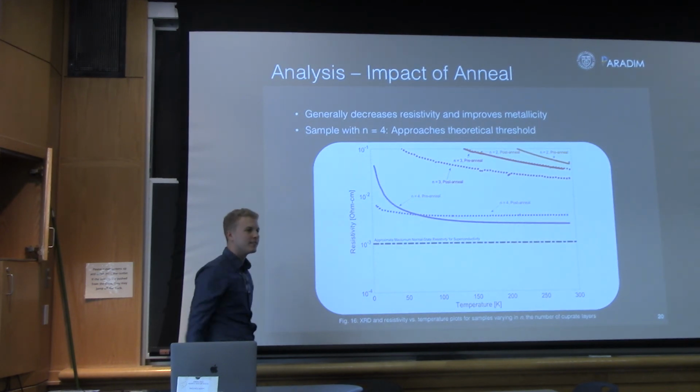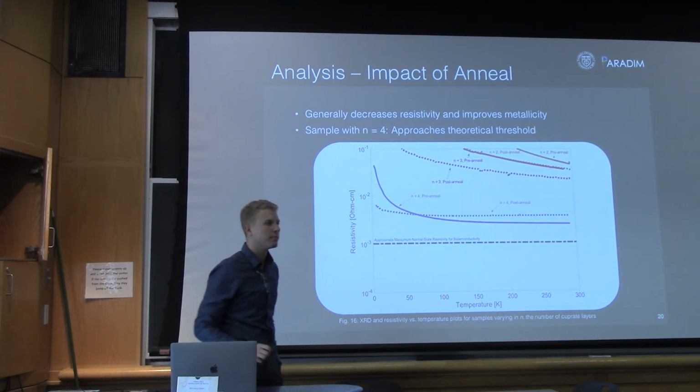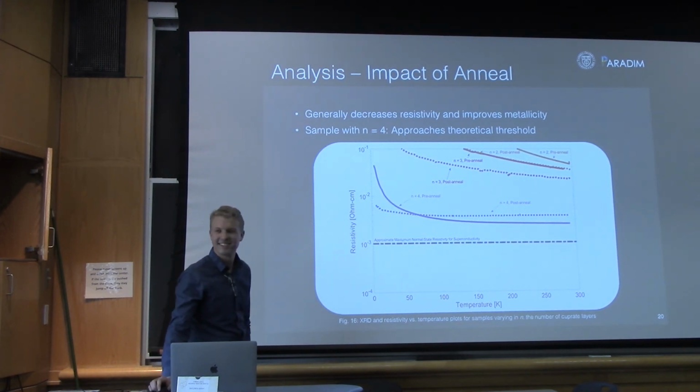And each scan, you're just varying ozone concentration or temperature of the anneal? Yeah. Maybe we'll increase temperature from 200 to 250. Maybe we'll make the time 2 hours instead of 1 hour. So 3 variables then, okay. That's a lot of tests. Yeah, plenty of variables to play around with.